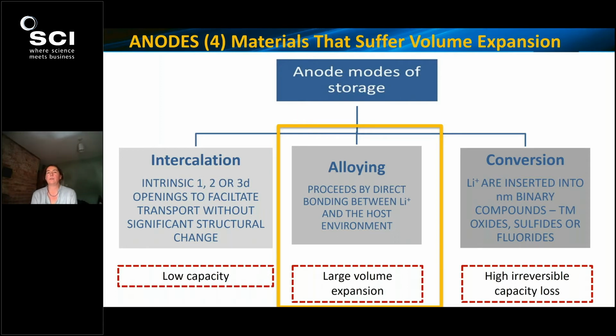But the last major categorization of anode issue would be down to the type of material and lithium storage mode. So there are 3 different modes of anode mechanism that insert lithium. Layered materials such as graphite, which were the initial anode materials, store lithium by way of an intercalation process, whereby it literally inserts itself between layers. And this can be intrinsic 1, 2, or 3D openings within the particles to facilitate transport. Now, this is great because we don't suffer from any significant structural change or expansion. But the downside of this is that they have limited storage capacity.